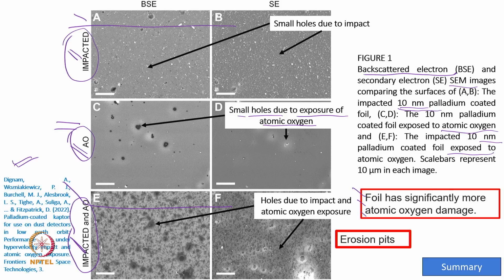So oxygen was a leftover fuel, and the policy was made that the fuel should be released in the environment, as it will not really cause debris. But the oxygen or atomic oxygen which is released in the environment itself increases the damage to the surface. So it is important to note that whatever we were thinking, that releasing atomic oxygen in Earth's environment or Earth orbit will not impact the surface, in literature it has been found that it really increases the size.